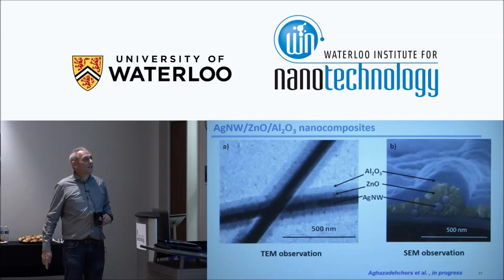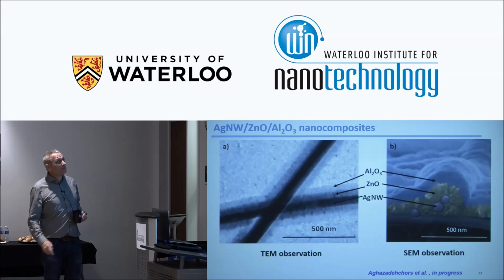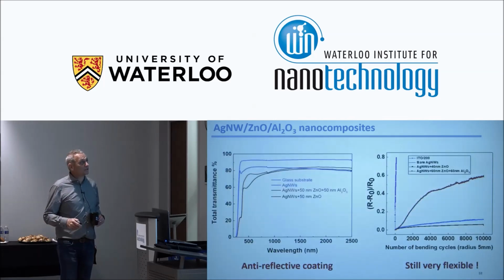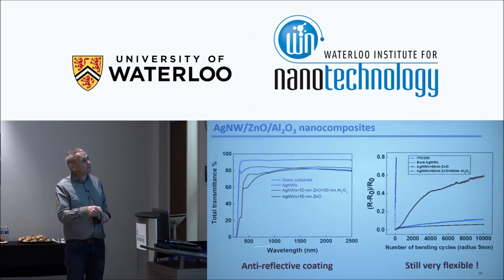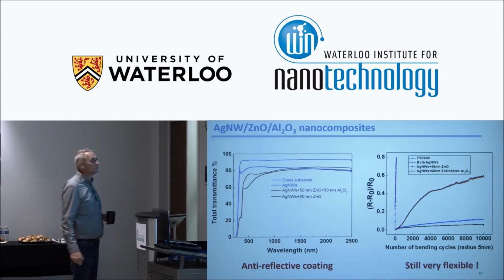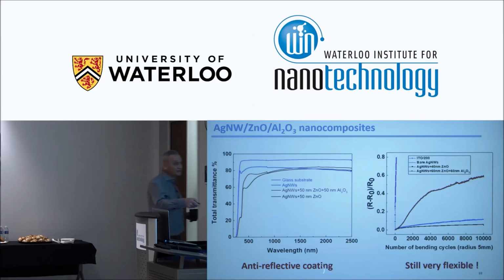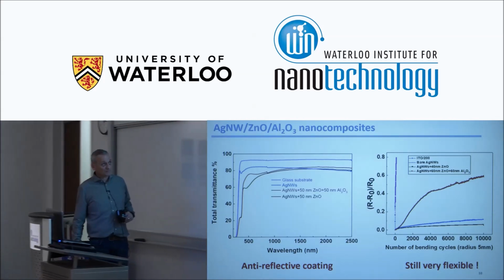Okay? And that's interesting because alumina could be used as a partial anti-reflective coating. This is transparency versus the wavelength, bare substrate. If you put only silver nanowires, or silver nanowires with zinc oxide, we have lower transparency, especially in the range between 400 and 800 nanometers, which is of interest for a lot of display and visible applications. And if we put, again, 50 nanometers of alumina, the optical transparency can increase quite well. So this is a kind of partial anti-reflective coating.